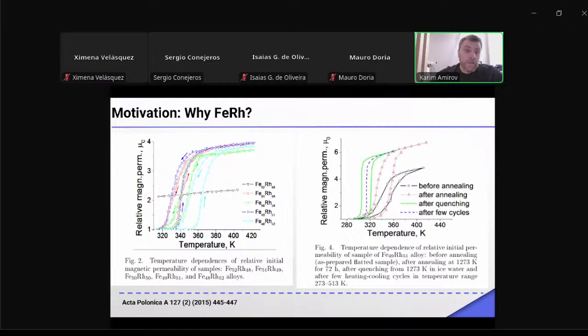So, as I noted, iron rhodium has a giant change of magnetization around the phase transition temperature, which is close to physiological temperature. Second, the phase transition parameters like hysteresis and the transition temperature can be tuned by annealing and chemical doping, and it's more controllable than in ternary alloys.